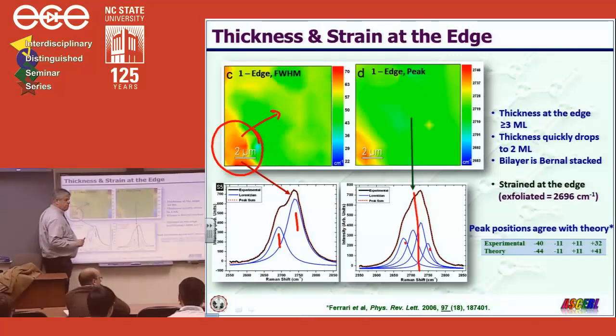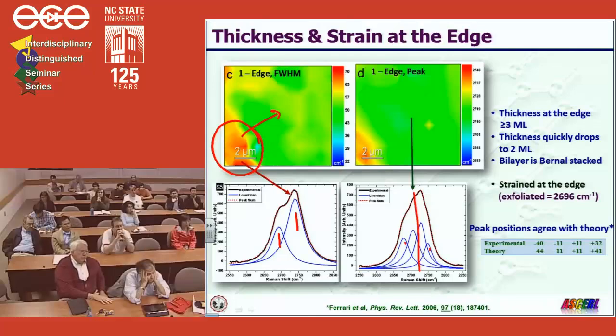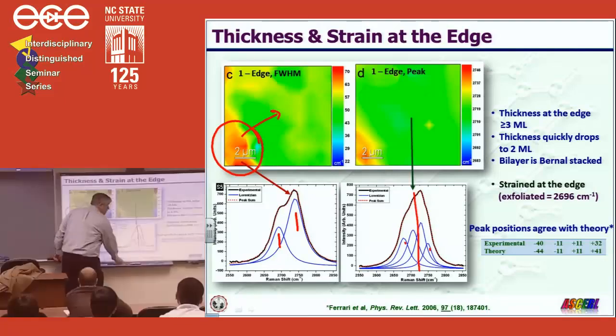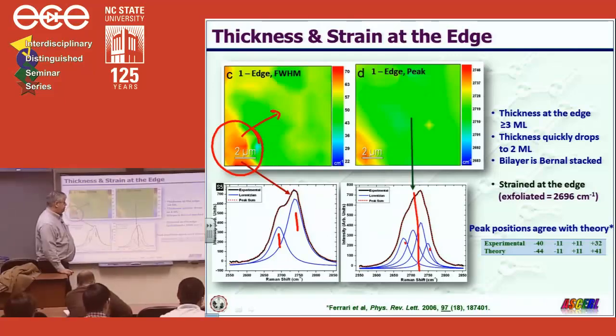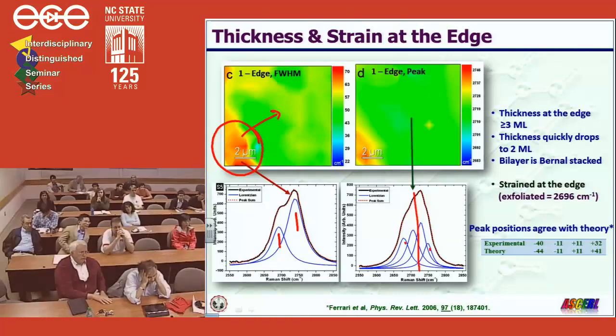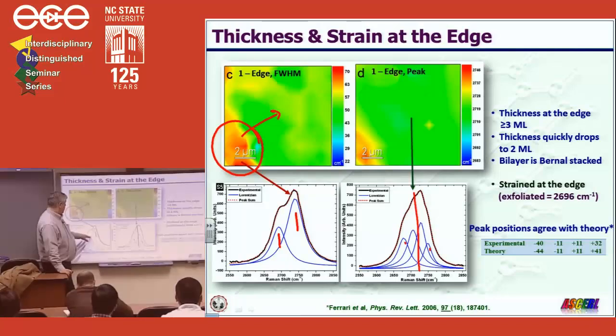Yes, John? When you do these fits on the Raman spectra, just looking by eye, it doesn't look like all the peaks have the same full width at half maximum. Is that a constraint that's put in, or are they just fit with numbers of peaks? No, the fits were actually completely unconstrained. Yeah, well, I think it would be interesting to try to see, because it looks like when you fit with 4 peaks that the peaks are narrower than the ones when you fit with 2 peaks. Well, that is true. I mean, this is just an artifact of the program attempting to duplicate the spectra.